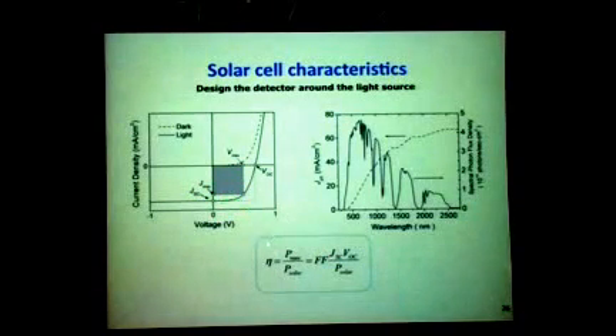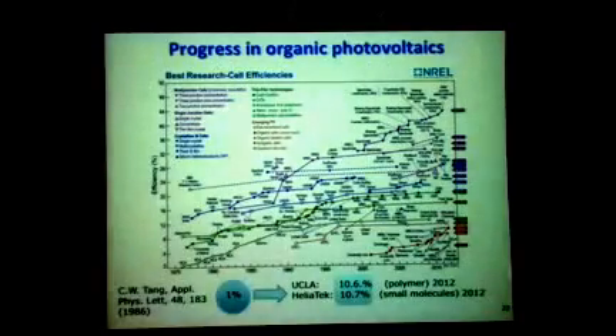You can define the efficiency as the product along that curve where photovoltage and photocurrent are maximized. Or it's also convenient to define it as a function of the product of the intersects with the horizontal and vertical axis, namely the open circuit voltage and the short circuit current. Then you introduce the fill factor, which is the ratio of Vmax times Jmax, the gray shaded area, divided by the area defined by the product of Voc and Jsc. So just to put organics into perspective compared with other PV technologies, there's good news and bad news.